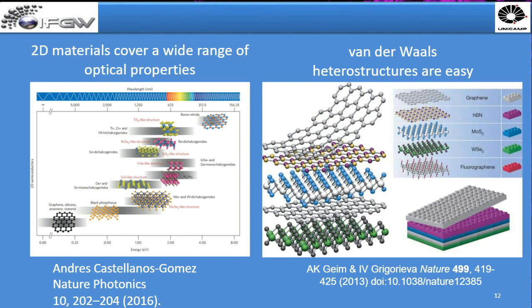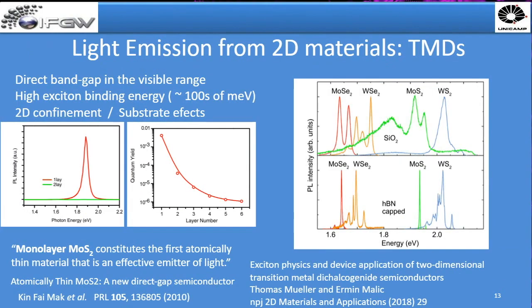And in the case of the tungsten selenides or these transition metal dichalcogenides, it's very interesting because they've been known for several years. So many people studied them many years ago, but recently, 12 years ago, people discovered that when thinned to one monolayer, they become a direct band gap. And this is very interesting because you have a new and interesting material with a direct band gap. And that's the kind of material that is really needed when you want to make an optically active device like an LED or something like that.